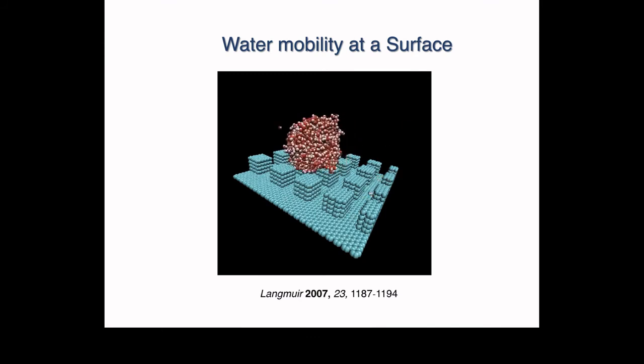So you can see the water, once it reaches the interface, it gets into the gaps and the holes, and the water molecules become trapped. So their mobility, the ones that are in the bottom of one of these little crevices, is highly restricted compared to the water molecule on the top. So you may be able to see one other application of this straight away is that we can look at mobility in pores. In fact, we can look at pore structure in materials.